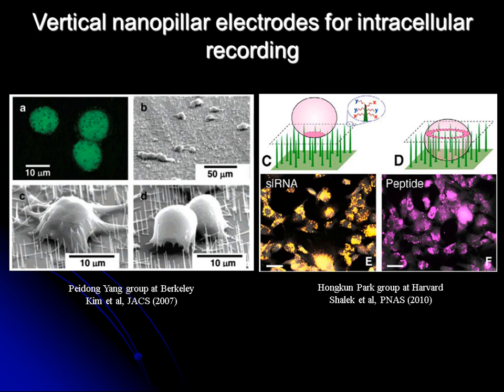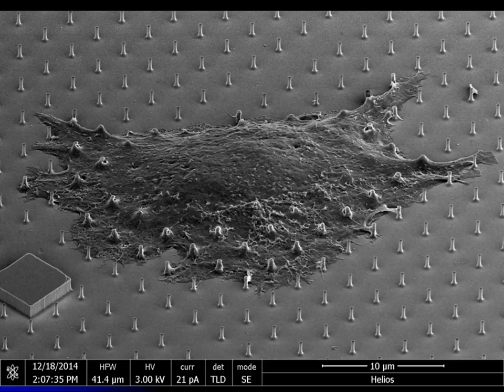So that gave us an idea. If we can use needles to record from the cells, then we can record intracellular action potentials without killing the cell. So we first tried to make a bed of needles, and then we grew cells on top of it. This is the SEM image. What you can see is a cell spreading well on many nanoneedles. In this particular case, it's around 20 to 30 nanopillars. We call them nanopillars. You can see the cell spreads very well, and in this case, the cell has been cultured for a few days.